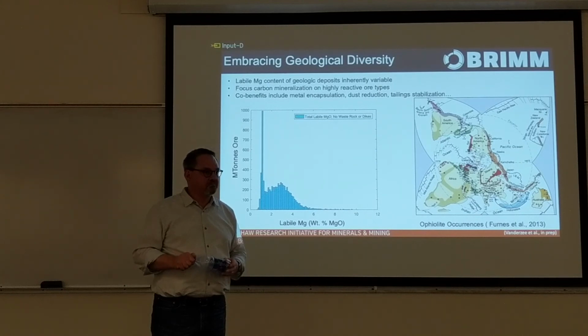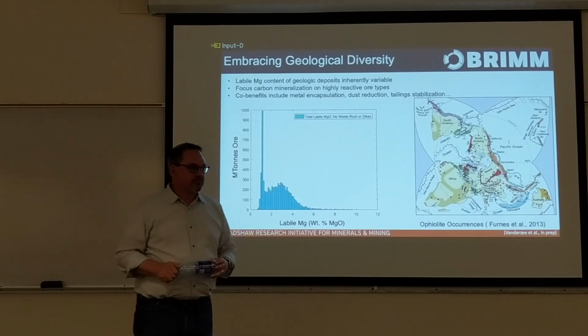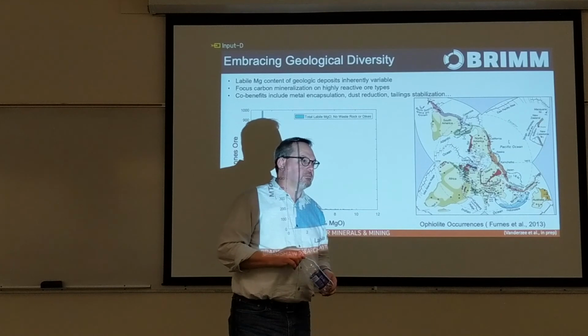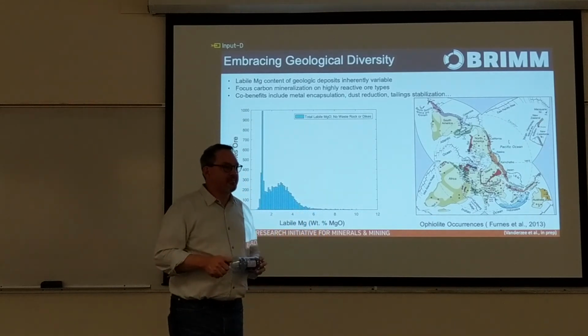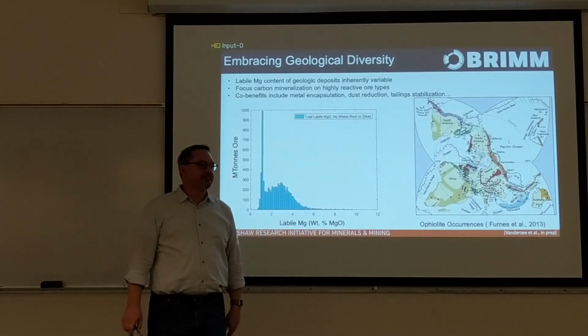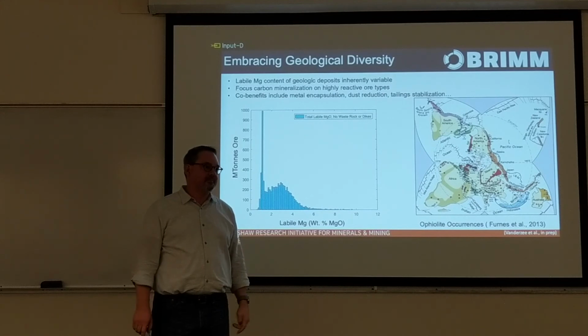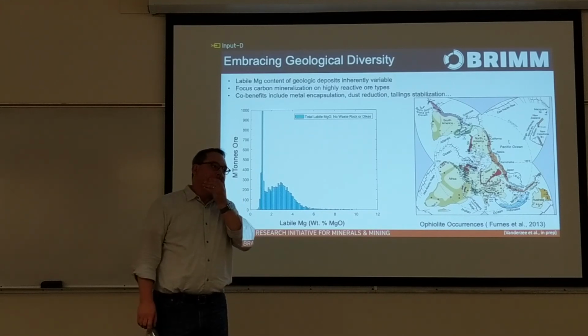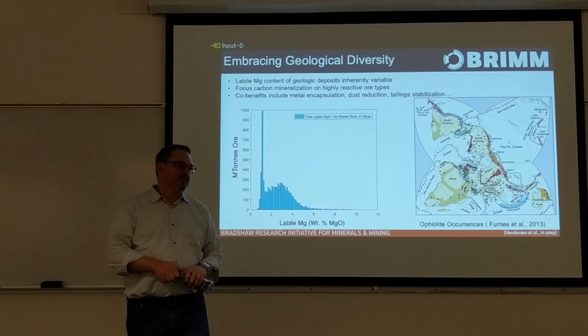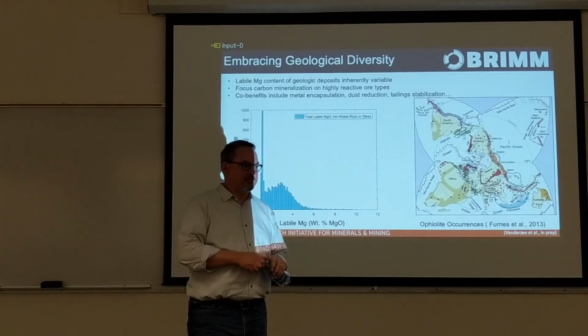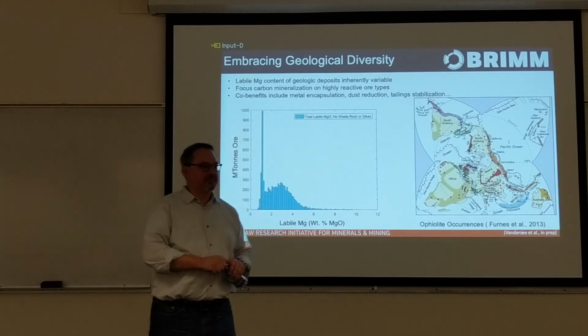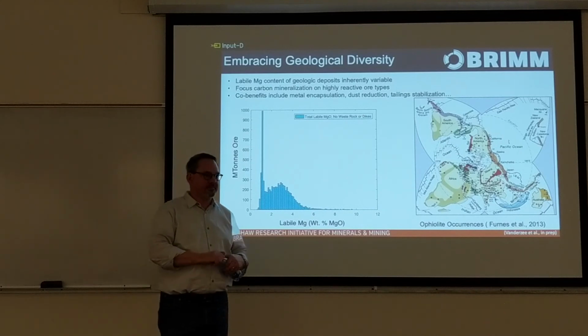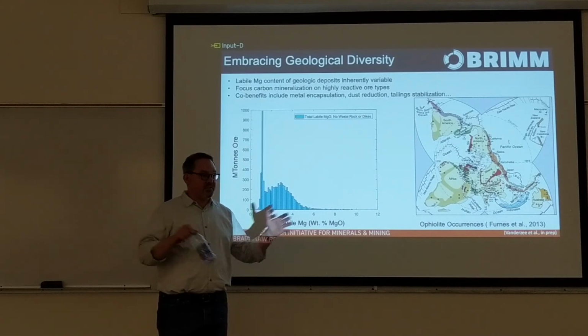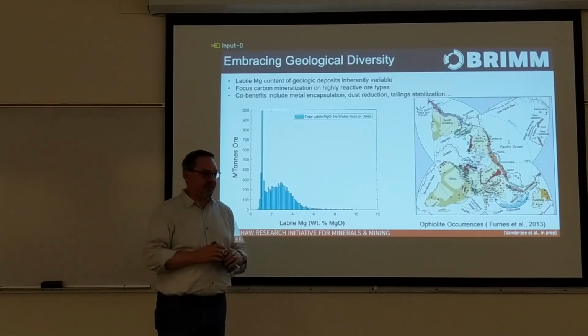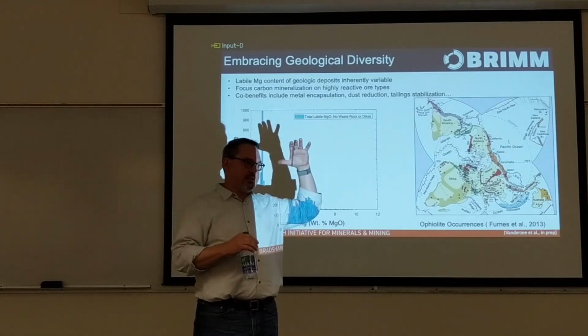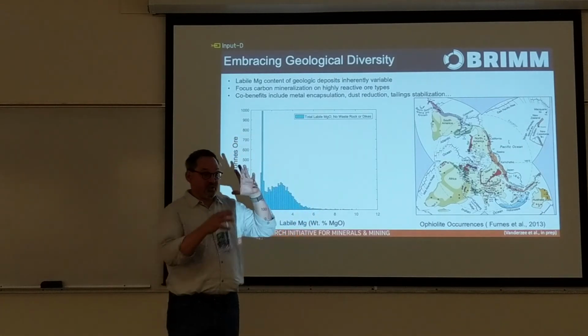The stuff with Siobhan, the first-order result is that carbonate mineralization transformation does not eliminate metals that are already there. That could be a potential downside, if every metal escaped the system, but it's not so, at least in that case, which is pretty cool. If you don't separate your dissolution from your precipitation, that's a replacement reaction, so you're doing your dissolution and precipitation all in one place.